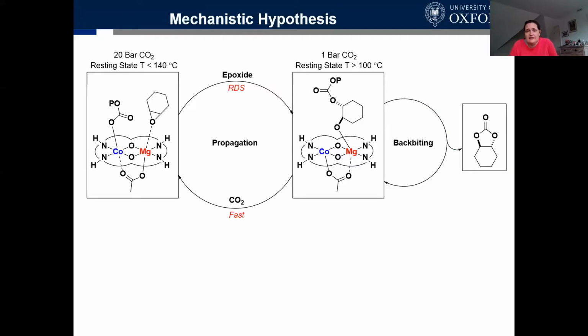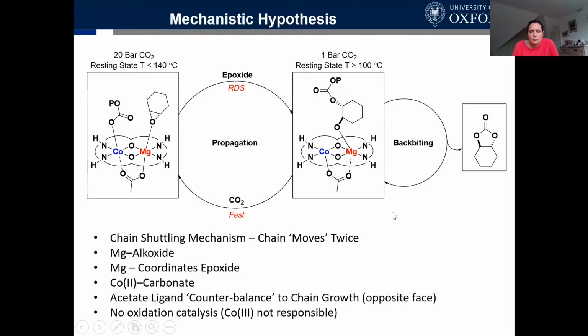So here we come back to our catalytic cycles, and we can say that provided that we have sufficient CO2 and we have temperature control, so that CO2 is dissolved, then we expect that CO2 insertion is fast and epoxide insertion is rate limiting. We have to manage this backbiting reaction, and that's important too. And the other point to make is that as we polymerize, this chain moves. So if you look at the formal site at which the anion is bound, on the left-hand side, the anionic portion is bound to cobalt in the carbonate form. But on the right-hand side, when we've transitioned into the alkoxide intermediate, it's now formally coordinated at magnesium.